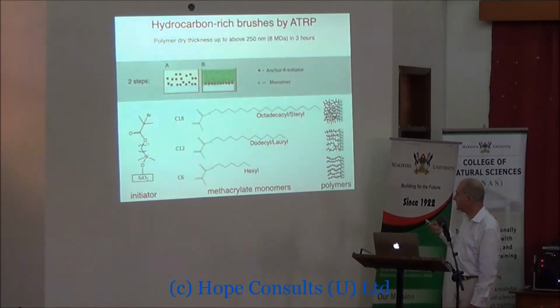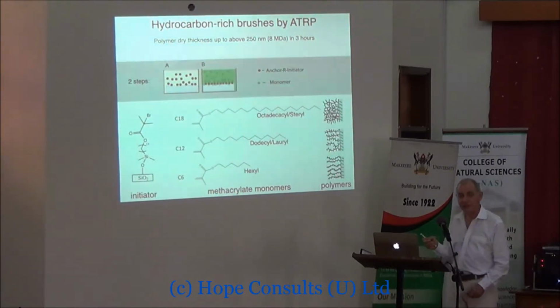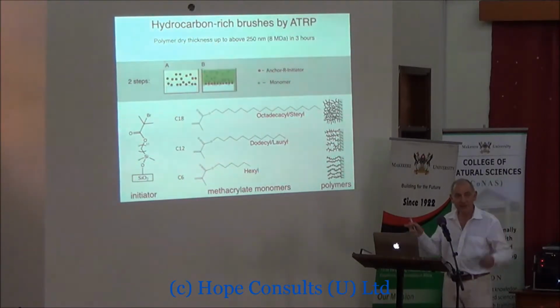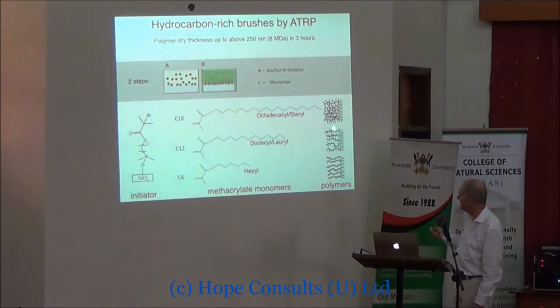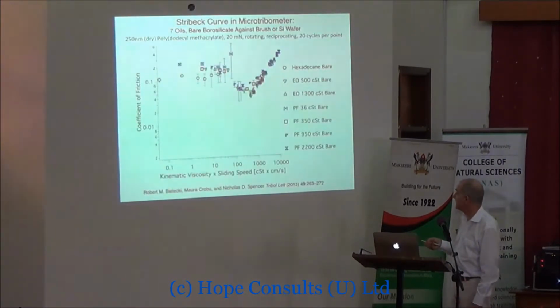And in order to make that happen, we put side chains on the side of the monomer. So this is the bit that polymerizes. This is what's known as an acrylate, which polymerizes very nicely by this ATRP technique. And then onto the acrylate we hooked a side chain. That meant that while this was polymerizing, it was producing a sort of Christmas tree structure where every monomer led to a side chain sticking out of the side. So we had this sort of structure coming out of the surface. And we had 3 different lengths of side chains just to see which worked the best in the kind of model oils we chose.